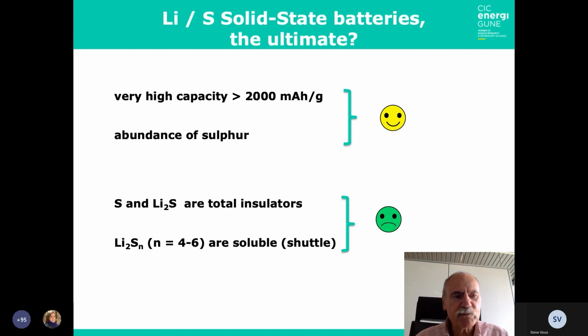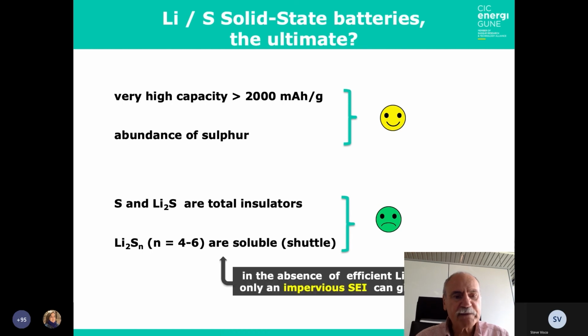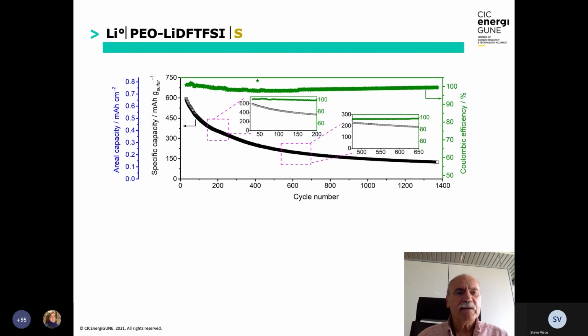And the polysulfides in between sulfur and Li2S are soluble in polymers or in liquid electrolyte and make a deleterious shuttle effect. And in fact, we can say that in the absence of a lithium SEI on the surface of lithium, we cannot expect to cycle a lithium-sulfur battery very well. And in fact, this was proven with a LiDFTFSI sulfur battery without taking any precaution. As you can see, a Coulombic efficiency could be kept for 1,000 cycles. The capacity was decaying, of course, but close to 1,400 cycles were obtained without any bad event on the cycle curve.